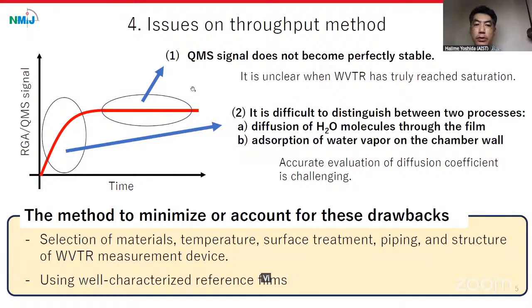However, the throughput method still has issues related to water vapor adsorption. First, the QMS signal does not become perfectly stable in this region. Therefore, it is unclear when the WVTR has truly reached saturation, and the signal typically drifts. Second, it is difficult to distinguish between 2 processes: A, diffusion of H2O molecules through the films, and B, adsorption of water vapor on the chamber wall. And this makes accurate evaluation of the diffusion coefficient challenging.